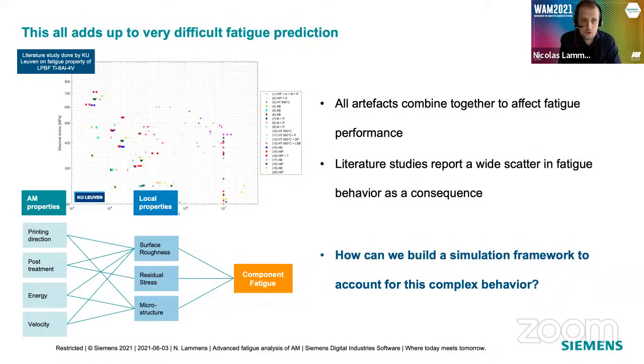Now, to be able to predict the performance of the component, there is a second challenge. You not only want to know all the properties or all these artifacts, but you also have to be able to know how these will work together to get to a certain fatigue life. And if you look at the top picture here, this is a literature study that has been done on additively manufactured Ti-64. And what you can see there is that depending on the precise type of processing that was done on the coupons, you get a fatigue life that has a huge variation. So this means that if you want to accurately predict lifetime of your component, you actually have to know pretty accurately all the process parameters or the precise condition of your component, because if you don't, you have no way of picking the right SN curve from this scatter plot.